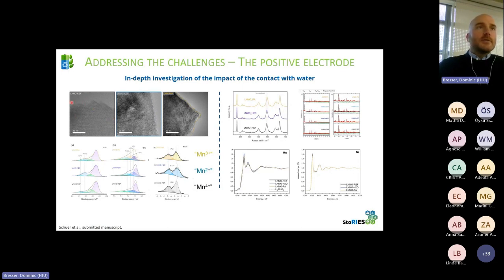In this experiment we did a very extensive comparison of lithium nickel manganese oxide that was not exposed to any kind of solvent, which is called the reference. Then lithium nickel manganese oxide that was exposed to water, and then lithium nickel manganese oxide that was exposed to an aqueous solution of phosphoric acid, so PA. For LNMO at least, and this is different for NMC type materials, we did a lot of characterization techniques: X-ray absorption spectroscopy, Raman spectroscopy, X-ray diffraction, neutron diffraction. And you could hardly spot any impact on the bulk of the material.